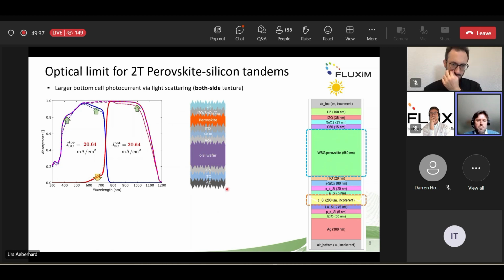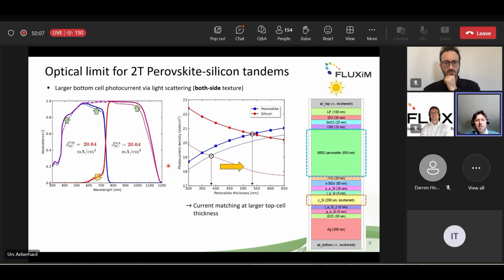But this is not the end of the story, because you could also have a double-side texture. And in this case, we assume not a planarized perovskite, but this conformal coating that I can also mention. This gives you an additional current, not only in the bottom cell, but also in the top cell. So again, this is the situation that is already optimized with regards to current matching. And since we have now larger absorption in the silicon, also the optimum thickness of the top cell of the perovskite shifts to a larger value. So we had for the flat case 380 nanometers. For the fully textured, we have 530 nanometers.